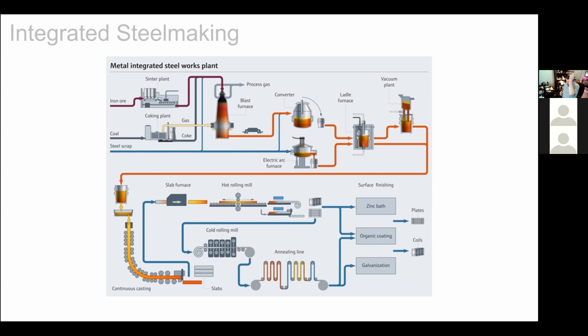So what a lot of people do now is they take waste iron products that contain iron oxide along with some iron ore, and they will add that into this furnace and produce this material, which is then broken into smaller pieces after it exits the furnace, and that can get charged as the feed material to the blast furnace. And this is very common in China, and also to a certain extent in Europe.